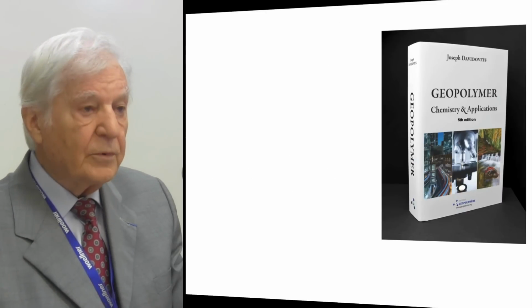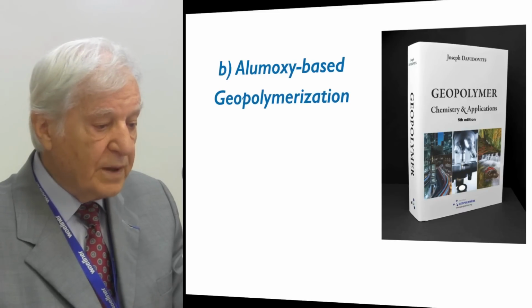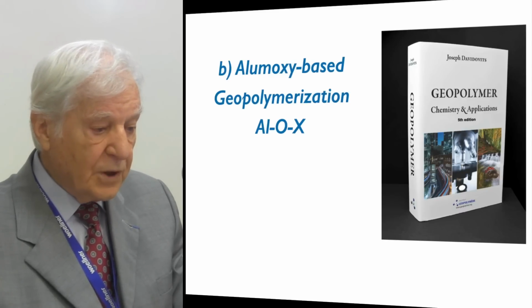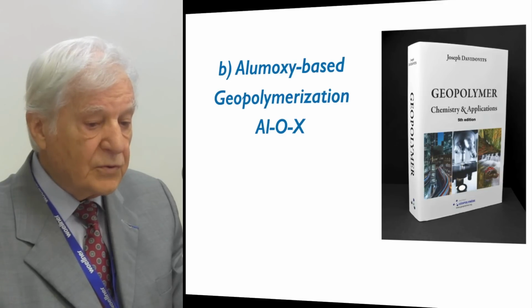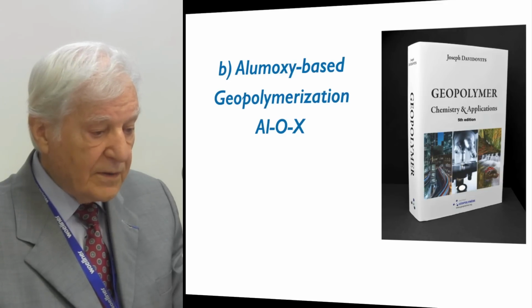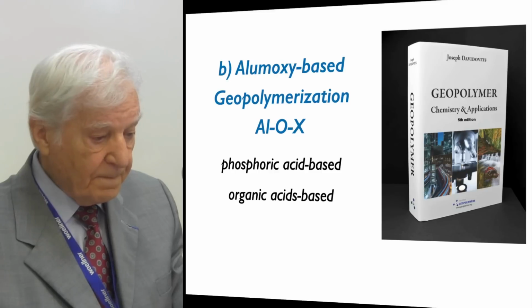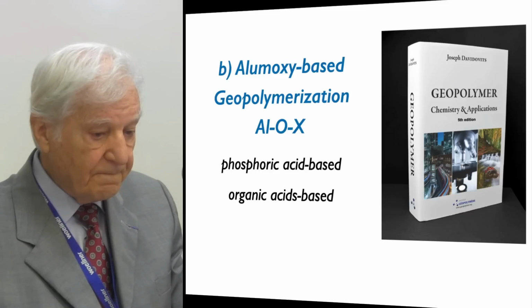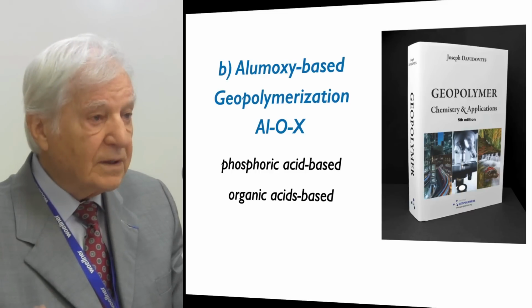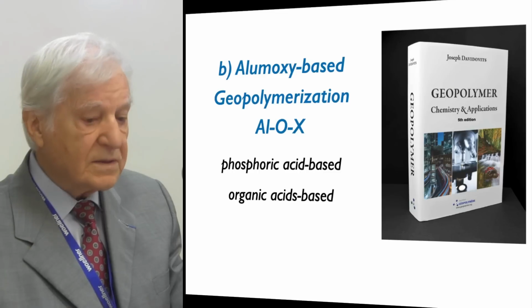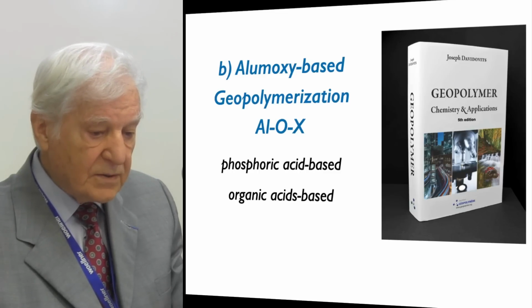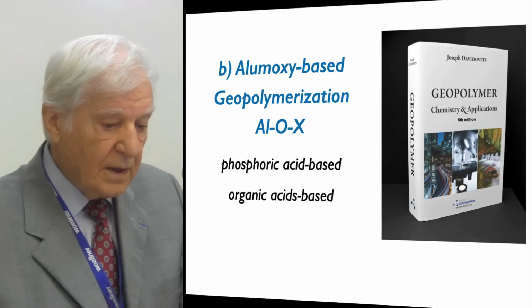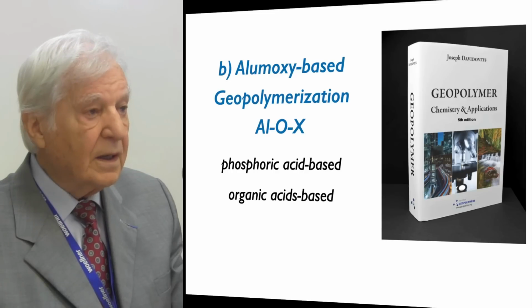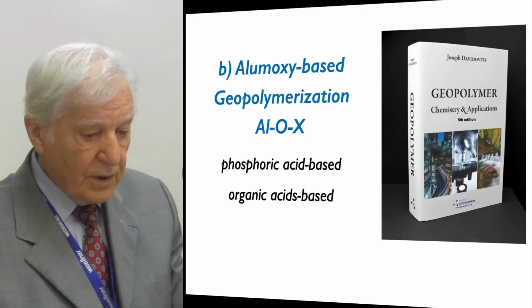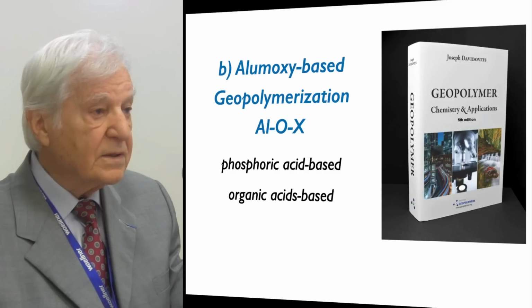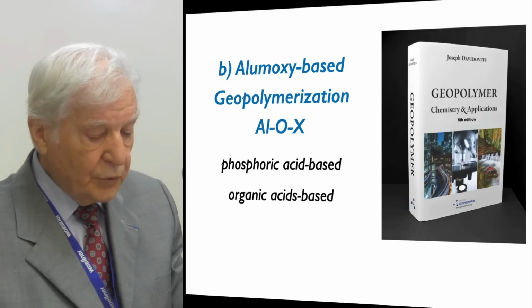The second geopolymeric system is the Alumoxy-based Geopolymerization that we call ALOX. It uses an acidic medium, either phosphoric acid-based or organic acids-based. Metakaolin is always reacting with these acids. The geopolymerization mechanism of the alumoxy-based geopolymers is different from the alkaline-based. It starts with the decomposition of the aluminosilicates into two units.